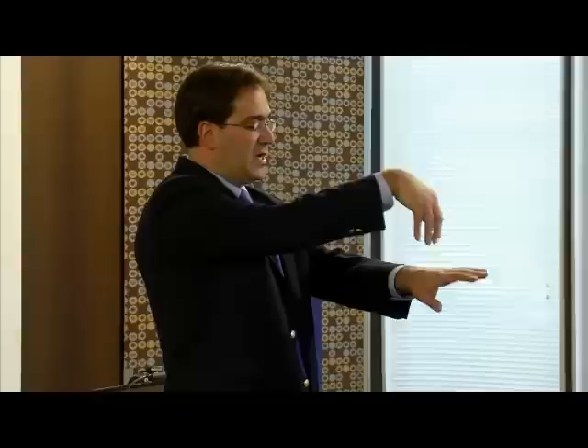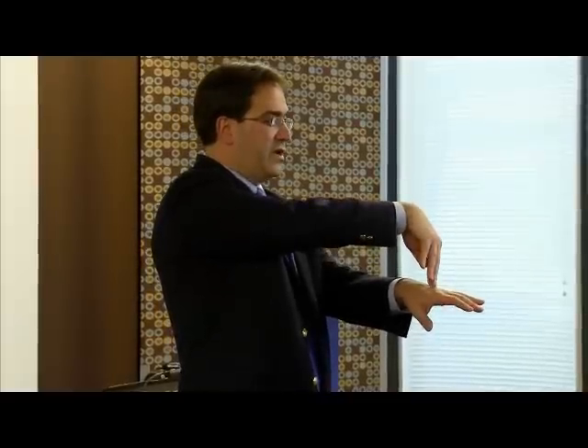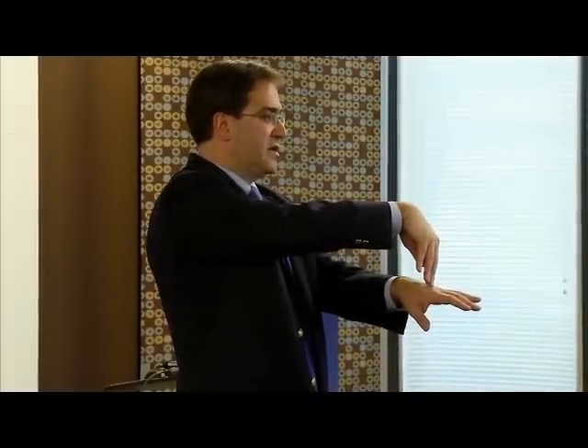I was intrigued by your slide where I think you used the Greek letter phi for an angle or two angles. You mentioned that it was off by just a little bit either way, basically didn't work, and you had this fairly narrow peak in the middle. Right. So that's where you've got it perfectly level, and all the tips are in contact with the surface, and you're using the scale to measure the contact force. And so it turns out if you're like this and you've got, let's say, 80% of the tips in contact and 20% out of contact, you're somewhere over here on the other side of the peak. But as you adjust and get to this point, there's a very sharp rise in terms of contact force, which can be extrapolated from the weight measurement.